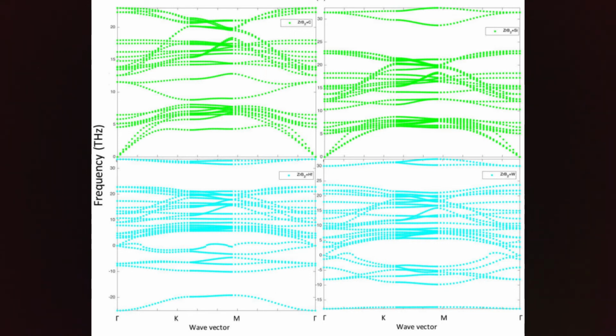For metallic impurities, negative phonon, which is the imaginary branches, demonstrate the dynamic instability for both configurations. The development of near zero frequency phonon transitioning between normal and imaginary modes indicates changes in charge density area, showing that both metallic impurities have severely affected zirconium diboride's initial charge density distribution.